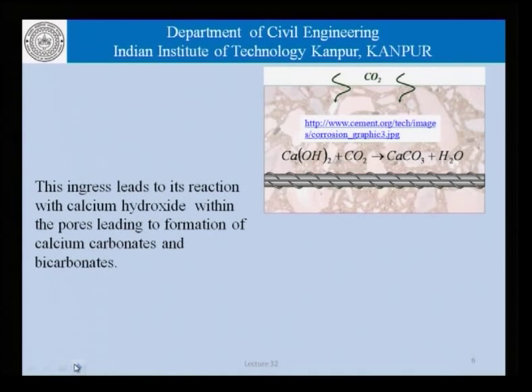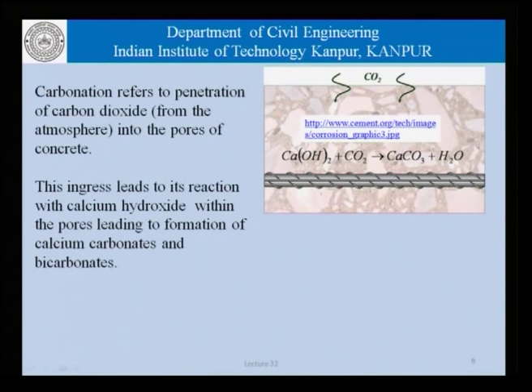Basically, concrete structures exposed to the atmosphere are exposed to a certain amount of carbon dioxide, and this carbon dioxide can penetrate into concrete through the pores which are there in concrete. And these pores and pore spaces, the kind of volume of pores, all those ideas have been talked about earlier. And we know that on account of hydration, a lot of calcium hydroxide is available in the pore spaces. Now, as far as carbonation is concerned, all concrete structures in the atmosphere are exposed to a certain amount of carbon dioxide, which can obviously permeate into the concrete through the pore spaces which are there on account of the normal porosity, the genesis of which is arising out of movement of water which is left behind after hydration and so on.